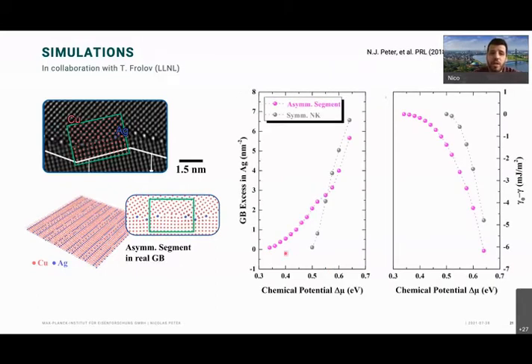We can also look now at how much silver the grain boundary can take up. The asymmetric boundary takes up, at a low chemical potential, so meaning there is little silver available, already a lot of silver, while the symmetric one does not. But once the symmetric one is there and the concentration is high enough, it takes up silver very much, and much more than the asymmetric one.